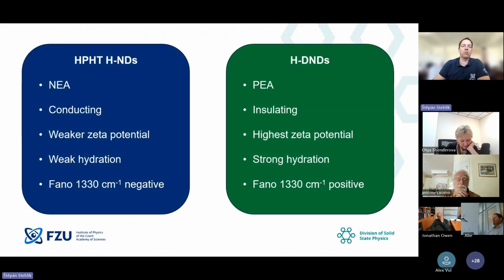Okay, so to quickly sum up this initial part, we compared the HPHT nanodiamonds and the DNDs, and we saw quite different behavior. So here we see the negative electron affinity, the conductivity behavior. We saw the weaker zeta potential and weaker hydration, and we saw in IR this negative Fano-like feature. But in DNDs, we saw the positive electron affinity, insulating character, highest zeta potential, very strong hydration, and we saw a peak at this Raman frequency.